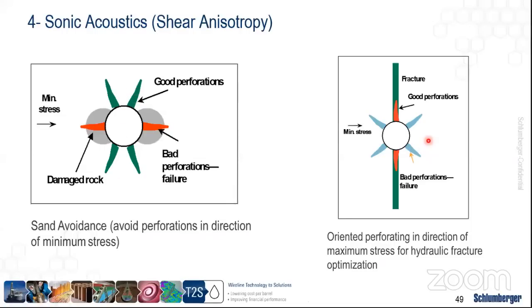Same goes with us designing the perforation itself. When we start to frac the job, or do the fracking job, we need to understand where the fast shear azimuth direction is, in order to frac in the direction of the maximum horizontal stress. And in this case, it will be in this direction, since it's orthogonal, or 90 degrees offset, from the minimum stress. If we frac in these directions, the amount of penetration of the frac itself would be very limited, and it would be very small compared to if we frac in the direction of the maximum horizontal stress.